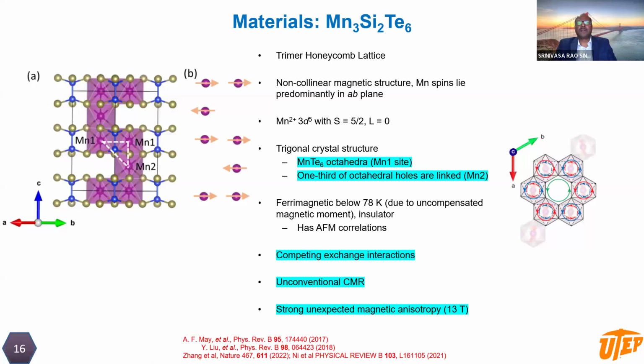Recently, this compound received a great deal of attention, particularly for its unconventional CMR, that is, colossal magnetoresistance. This compound shows unconventional CMR when we apply a magnetic field along the hard axis. In general, compounds exhibit CMR when you apply a magnetic field along the easy axis. And another interesting observation people made recently is that though the orbital angular momentum is almost zero, this material shows unexpected magnetic behavior,